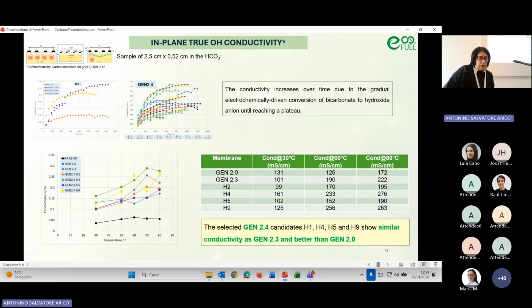So in this graph is reported the comparison among the benchmark, the previous generation, and the 4 selected membranes as a function of the temperature. And we can see that the membranes of Gen 2.4 show similar conductivity to Gen 2.3 and better than Gen 2.0, but also higher than the benchmark, that is the lowest.